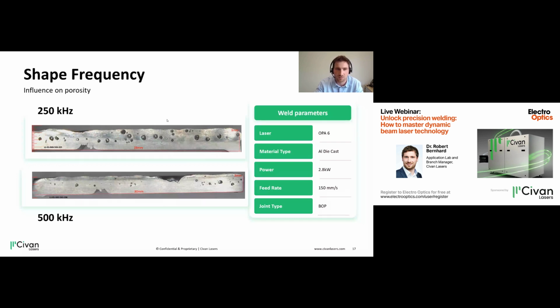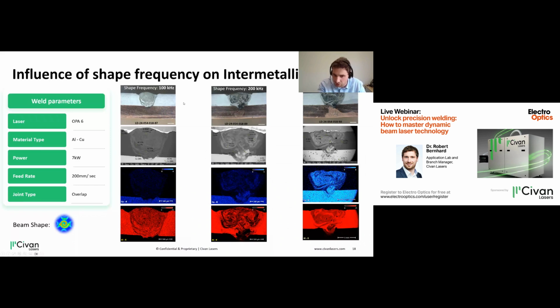This here is a bead on plate with 2.8 kilowatts and 150 millimeters per second. So you can see that we are able to reduce porosity when welding these materials with a high amount of porosity. But that's again not all. We're talking about more influences we have, and still with the shape frequency, it's also about intermetallic mixing.